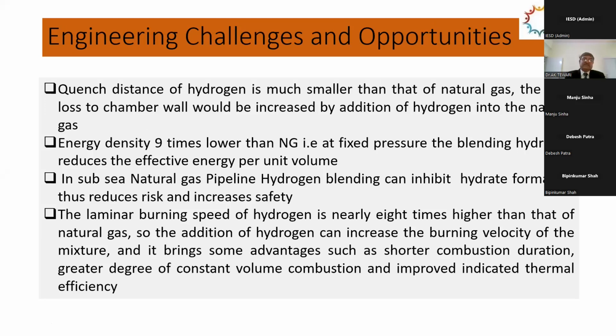Quench distance of hydrogen is smaller, so heat loss to the chamber wall would be slightly increased by the addition of hydrogen into the natural gas. Energy density is almost 9 times lower, so blending reduces the effective energy per unit volume, and that possibly requires higher compression too.